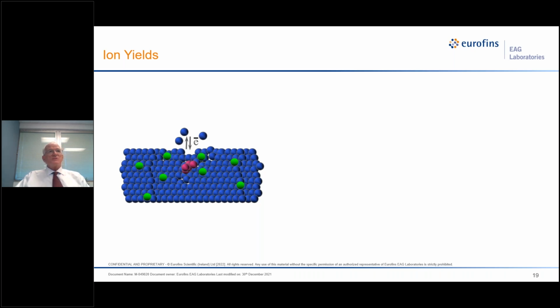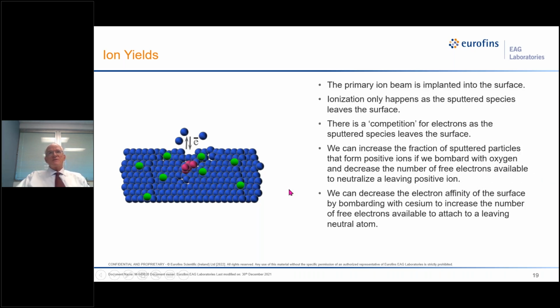So it has really good sensitivity that the inherent physics of XPS can just not match. But the primary particle becomes embedded in the sample, and as the surface recedes into the bulk, magic things happen. The primary beam is implanted into the surface, and ionization only happens as the sputtered species leaves the surface. So there's a competition of electrons from the sputtered particles. With oxygen bombardment, we can increase the fraction of sputtered particles that form positive ions, and decrease the number of free electrons that are available to neutralize a leaving positive ion. And we can bombard with cesium, and decrease the electron affinity of the surface, and increase the number of free electrons available to attach to a leaving atom.